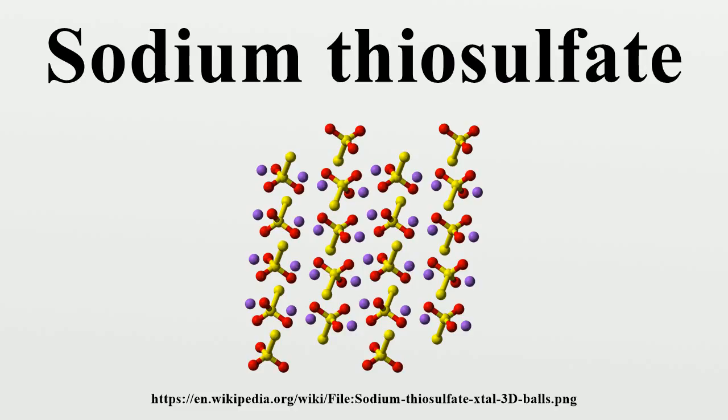Some problems with this alternative process include the high consumption of thiosulphate, and the lack of a suitable recovery technique, since [Au(S2O3)2]^3- does not adsorb to activated carbon, which is the standard technique used in gold cyanidation to separate the gold complex from the ore slurry.